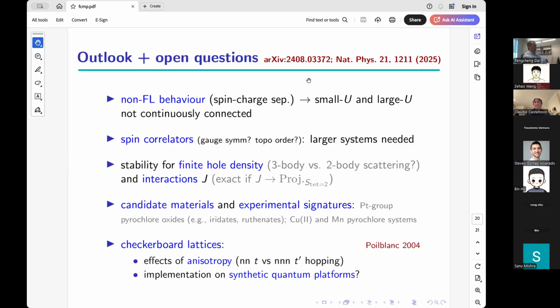What about candidate materials? There is the platinum group pyrochlore oxides, iridates, ruthenates, have an interesting phenomenon. The iridium site has essentially spin a half emergent degrees of freedom, and then if you dope them to 4+, they become spin 0. So they are sort of the ideal setup, and pyrochlore, very regular pyrochlore lattice. However, they have strong spin-orbit coupling and anisotropy, which are not present in the Hubbard model we used. Therefore, we would need to check whether that throws away all of the physics we are interested in.